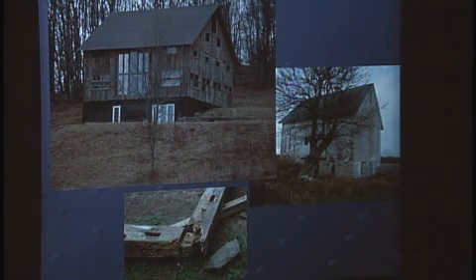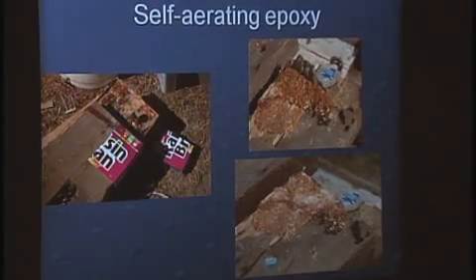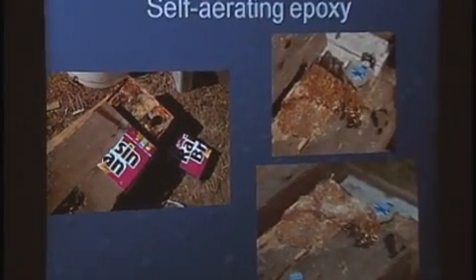So on some of the timbers, I actually did recut replacements, but on this one, I decided I was going to try to actually cast in place an epoxy fill. Now, one of the issues, again, with epoxy is it tends to get very hard, and comparatively, it yields a margin, an interface that is very brittle and fracturable. So what I did was to take one of those timbers and, following the same type of approach, made a box that was the right size. It's the mold into which I packed wood shavings, and into that I mixed up and poured epoxy.